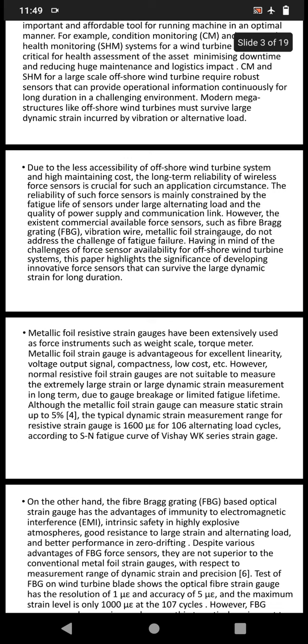Metallic foil resistive strain gauges have been extensively used as force instruments such as weight scale, torque meter. Metallic foil strain gauge is advantageous for excellent linearity voltage output signal, compactness, low cost, etc. However, normal resistive foil strain gauges are not suitable to measure the extremely large strain or large dynamic strain in long term, due to gauge breakage or limited lifetime, although the metallic foil strain gauge can measure static strain up to 5%. The typical dynamic strain measurement range for resistive strain gauge is 1,600 mu for 10^6 alternating load cycles according to the S-N fatigue curve of Vishay WK series strain gage.